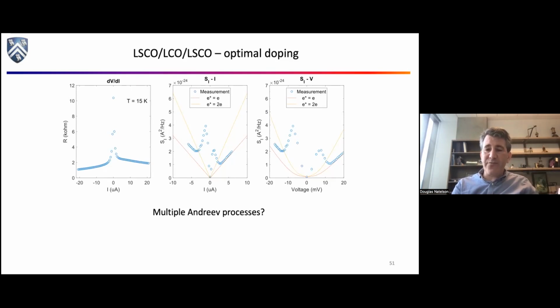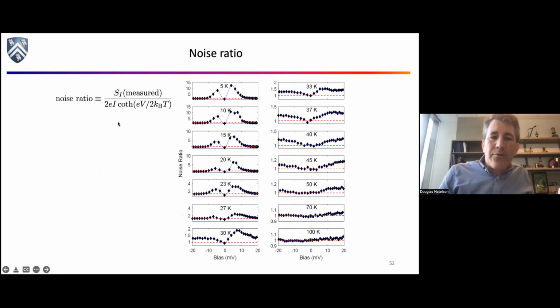So we can plot this in a different way. What I'm plotting here is something we defined called the noise ratio. It's basically the measured noise divided by the single particle tunneling expectation. And here we are at 100 Kelvin. Pretty much this ratio is 1, maybe a little bit of a deviation. But as you start cooling down, you can see it starts to deviate from 1, pretty warm. And again, we're well above TC, but this deviates a lot. And then, of course, like I said, wild things happen well below TC.